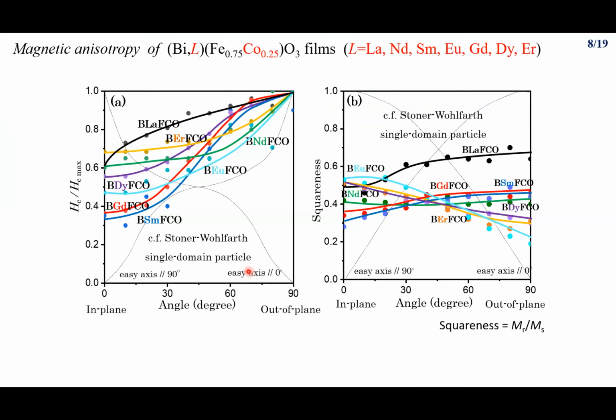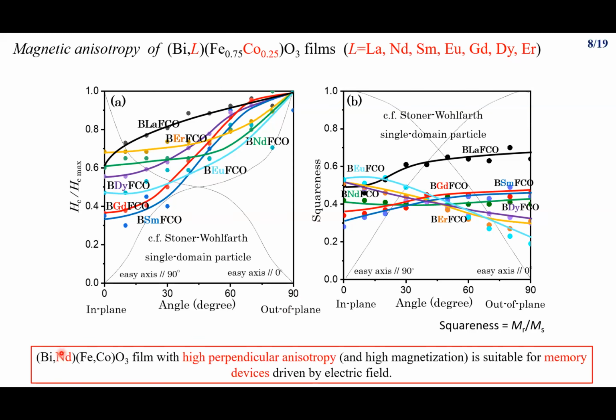So if we think about the perpendicular magnetic anisotropy, as I explained before, I checked the perpendicular anisotropy by the Stoner-Wohlfarth single domain particle model. By changing the angle between the thin film and the external magnetic field, I could see here that it achieves a perpendicular magnetic anisotropy maximum at 90 degrees. That means it shows PMA. And this neodymium substituted film, as I said, is better for the memory devices, and here also I showed that it has very good PMA, so I can use it in memory device applications.